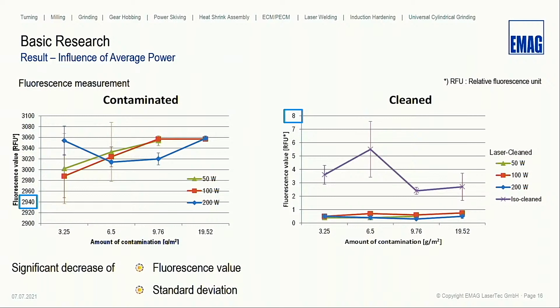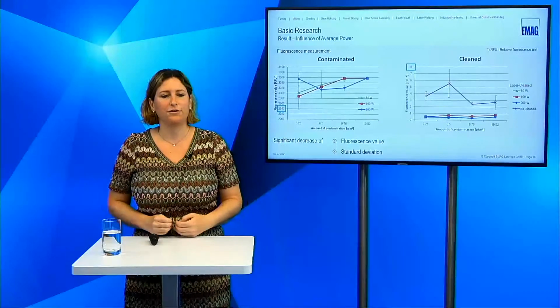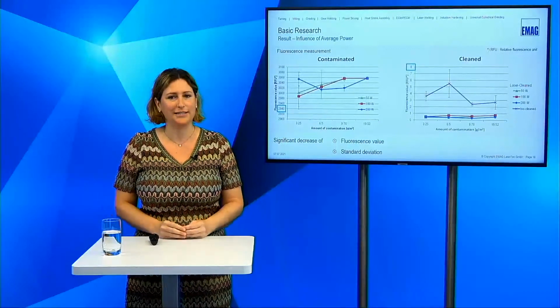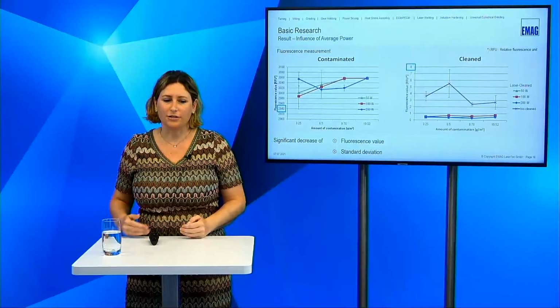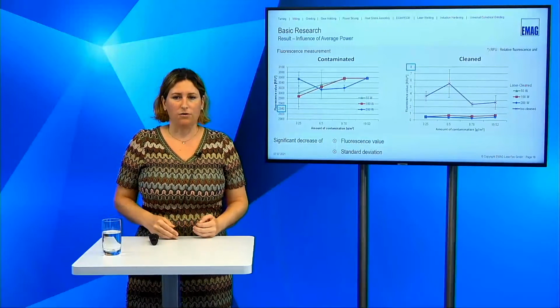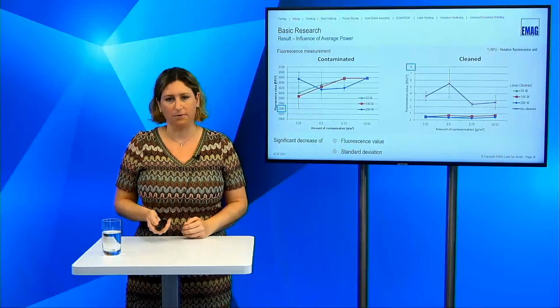So it depends really on your following process. If a 5 might be enough for a laser cleaned surface, a 15 might be enough for another. It depends on the process afterwards, if it's okay or if it's fine with also some more contamination on it. And what you can also see for the fluorescence for the laser cleaned surface, you have really a constant value. Over the whole surface you measure, you have almost the same value.